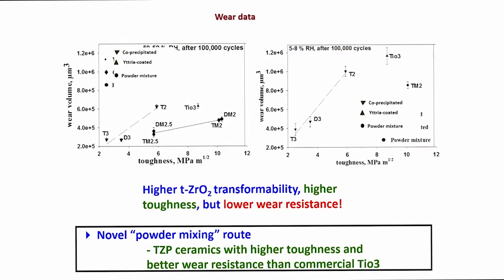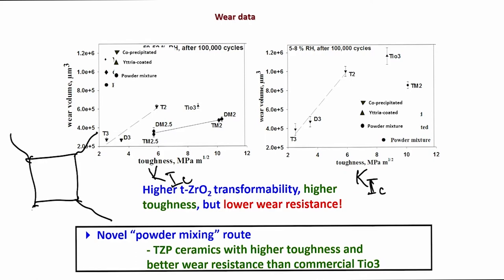Now one of the intriguing results is that when you measure the wear volume and plot it against fracture toughness, that is K1C, which is measured using the indentation cracking method here. Indentation cracking means you take a Vickers indent. In ceramics, Vickers indents cause cracking. Then you measure the total crack length 2C and the indent diagonal 2A, and from these measurements you can find the fracture toughness K1C values.